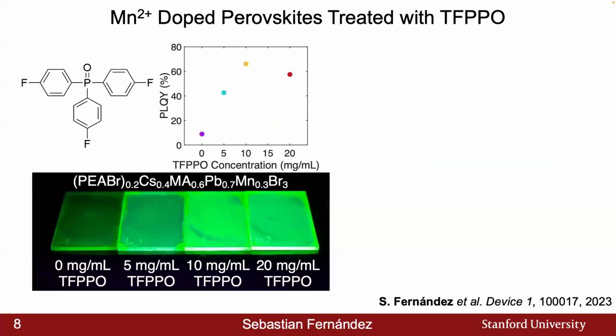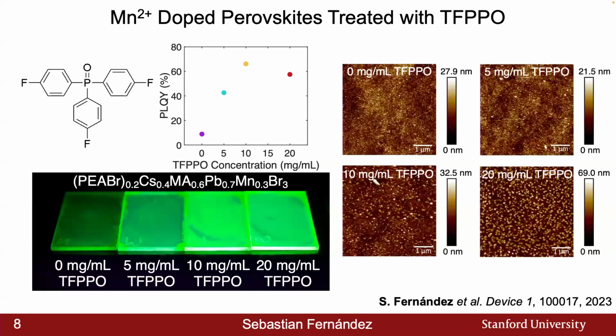And we can see that we can improve the photoluminescence quantum yield, which here is defined as the number of photons being emitted from the thin film to the number of photons that are absorbed by the thin film as well. We're reaching PLQYs of around 67%, which is over 2x the 2019 value. From the picture down below, we can also see the stoichiometry of the hybrid quasi-2D/3D perovskite that we've created. Under UV light, we can see in general that the emissivity of the thin film is increasing with TFPPO concentration. Also, looking at the atomic force microscopy images, we can see in general a change in the morphology of the thin film. And nevertheless, we then look at integrating these thin films into LED devices.